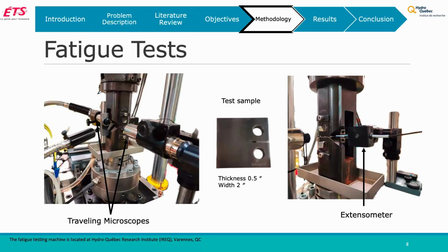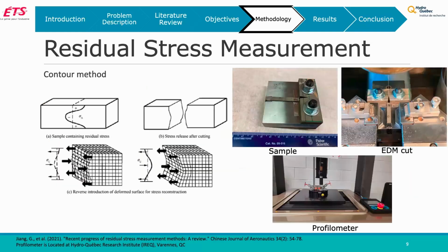The compliance method is used to measure the crack length. Also, it was verified optically by a traveling microscope and others. Residual stresses were measured, and we did that using the contour method.